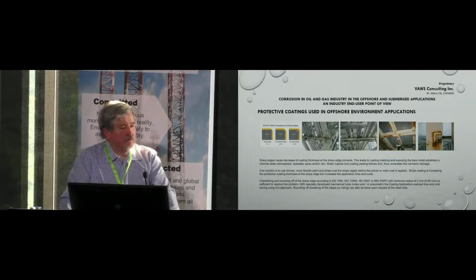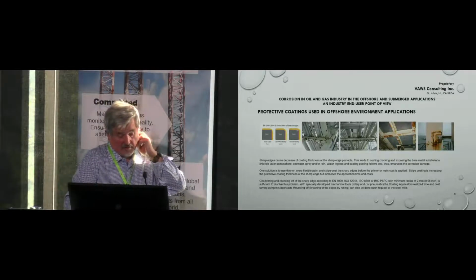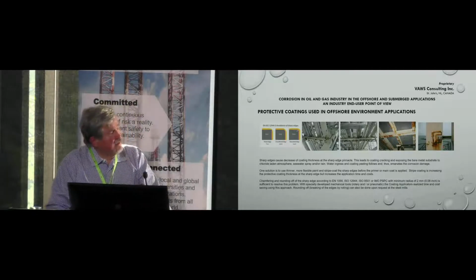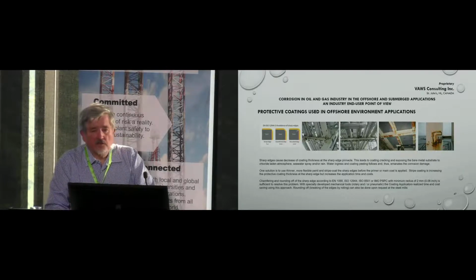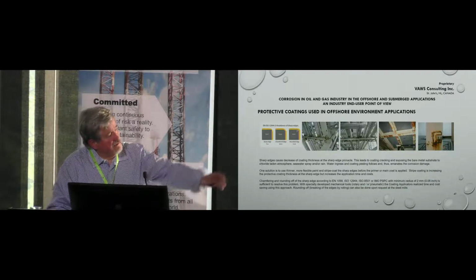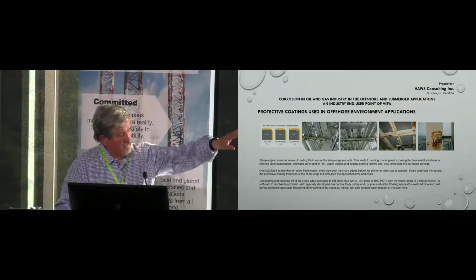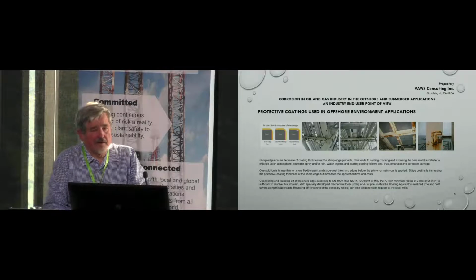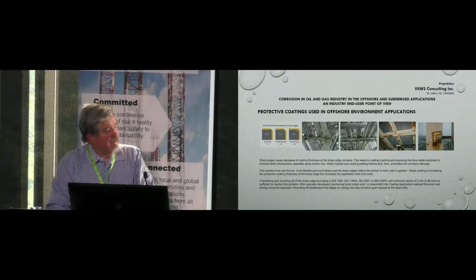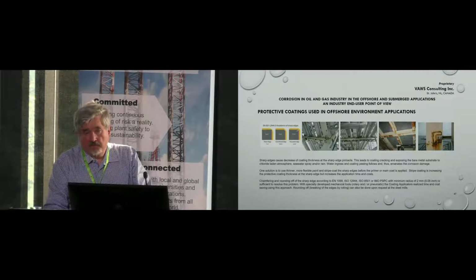The biggest problem with new construction is that, and we changed our specs, well, my past employer, the industry was very resistant to rounding edges for paint. You can see in all these examples that where the paint starts to fail is on the edges, because you can't paint a sharp edge. No way, there is no paint which will last on it. There is a method which is used quite extensively, and that's striping of the edges with a layer of paint, which only doubles the thickness of it, but it does not necessarily resolve the problem.